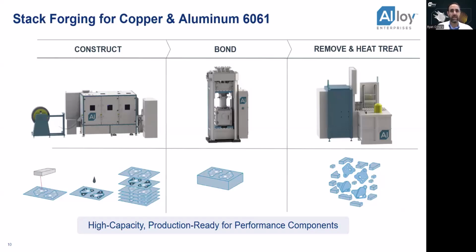Finally, the parts go through a standard heat treatment, leaving us with strong monolithic components that contain whatever internal geometries we designed in, such as microchannels or advanced thermal features. Additionally, for aluminum, we can achieve a full T6 high-strength heat treatment condition, and for copper, we are always in an annealed state. So in short, stack forging transforms low-cost sheet metal feedstock into high-performance single-piece parts with internal features that simply can't be made any other way.